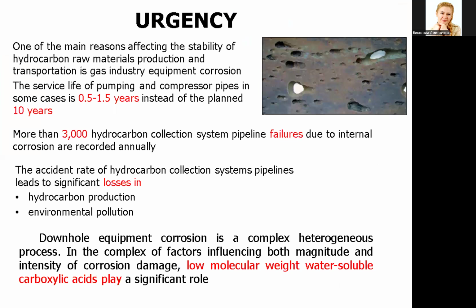One of the main reasons affecting the stability of hydrocarbon raw materials production and transportation in the gas industry is equipment corrosion. The service life of pumping and compressor pipes in some cases is 0.5 to 1.5 years instead of the planned 10 years. Downhole equipment corrosion is a complex heterogeneous process, and among the complex of factors influencing both the magnitude and the intensity of corrosion damage, low molecular weight water-soluble carboxylic acids play a significant role.